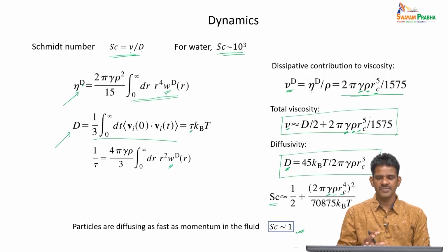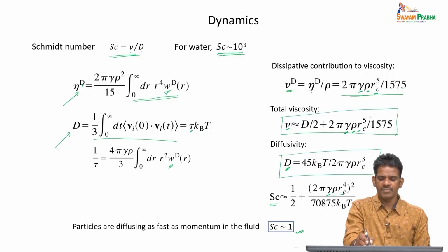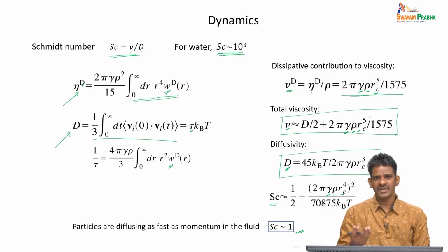If you have any simulation where mass diffusion is rate controlling or plays an important role, then DPD will have a very strong bias because of the incorrect dynamics. Ideally, one would like to have a Schmidt number of something like 1000 or of that order, but it turns out that while we enforce momentum conservation, hydrodynamic interaction, etc., dynamically we see a situation where the mass diffusion is quite fast, comparable to momentum diffusion.